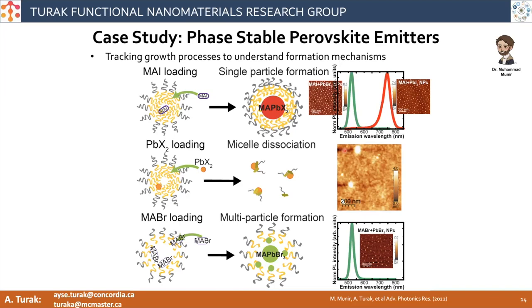And so, as I mentioned, if you change, for example, the order in which you load either the organic or the inorganic components, you can either get successful nanoparticle arrays or not. And if you change even the halide type, you might be able to get some nanoparticles, but your polydispersity goes bad because it's not possible using certain approaches. So understanding this interplay of the different components, how the metal interacts with the polymer, how the halide interacts with the polymer, gives you all these different knobs to turn to achieve a successful array.